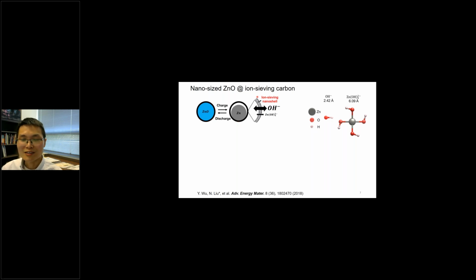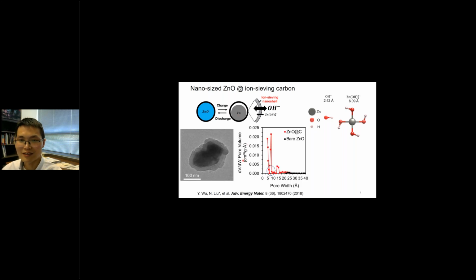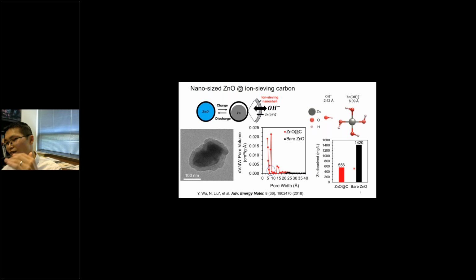But this shell has to allow hydroxide ions to come in, because that's necessary for the reaction to happen. We did the synthesis, and you can see this is the particle size, very small, and it has the shell. The shell is microporous, so it can block the zincate ion from escaping. And we indeed confirmed the confinement of the soluble zinc species inside the shell by doing this dissolution testing.